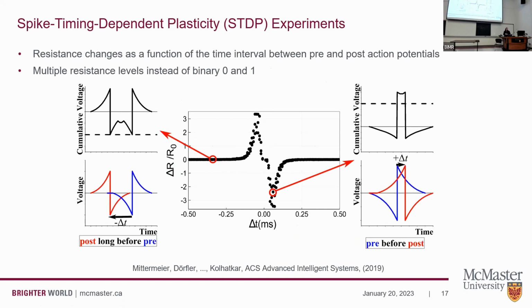The change in resistance can be directly reproduced in our resistive switching devices. They consist in applying those voltages and measuring the change in resistance as a function of the time interval between the arrival of those two pulses. So we obtained a curve that looks something like this. We have different regions, and let's look first at the region very far from the delta t equals 0. In this area, the resistance change is negligible. It's pretty much 0.